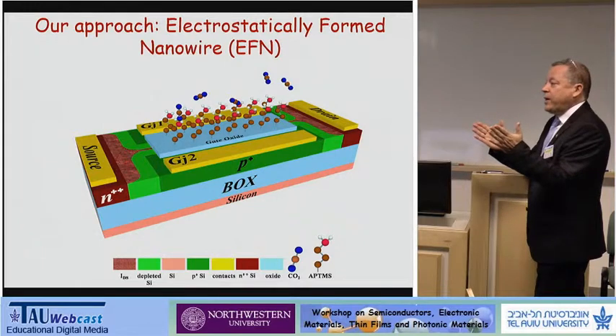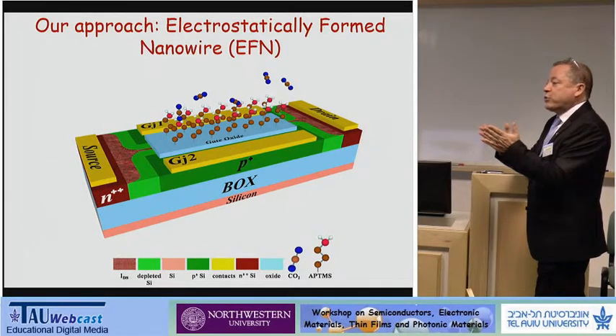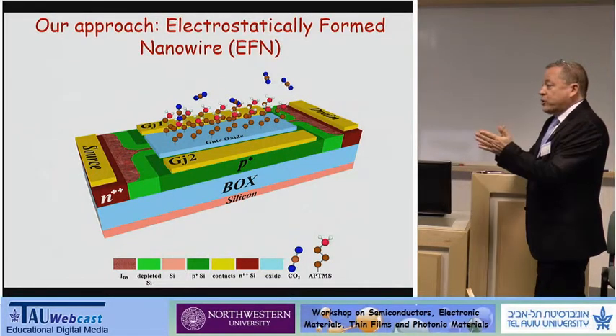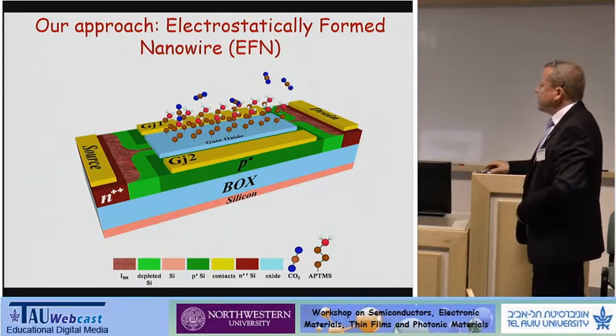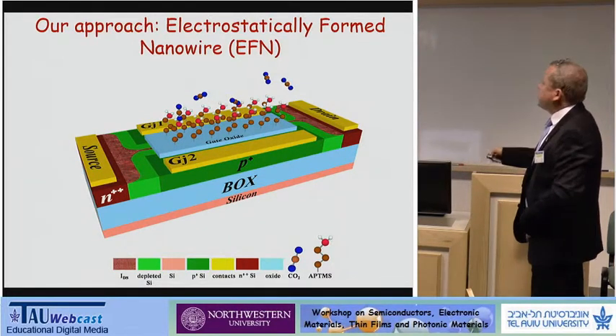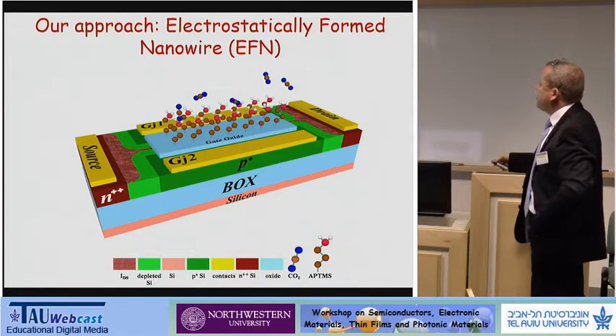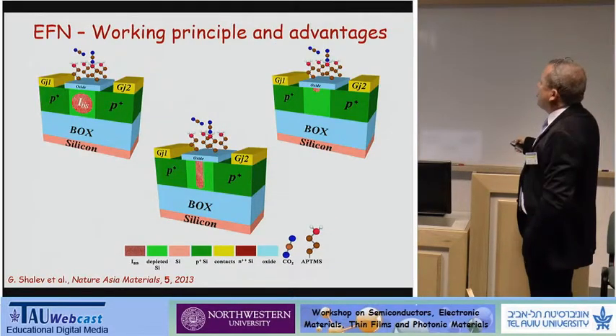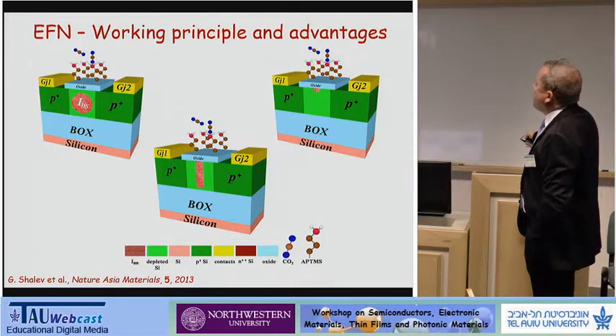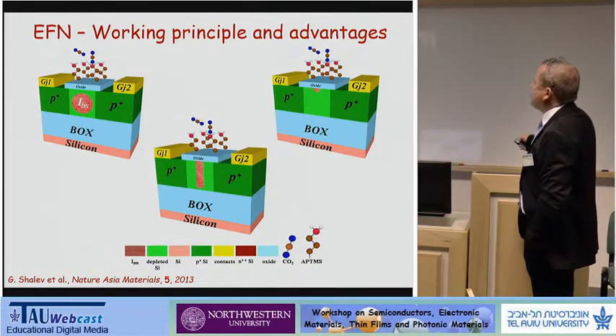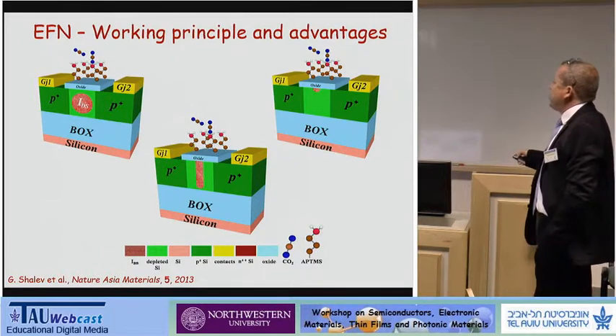So basically we apply negative reverse bias on these two diodes, and we shrink the carriers. The depleted regions extend, and we shrink the carriers to a nanowire-like shape, exactly a nanowire. You'll see it in a second. If I cross-section this device in the middle, ignoring these two, we form this kind of nanowire. And why is this close to the top dielectric? Because we have a backgate here.